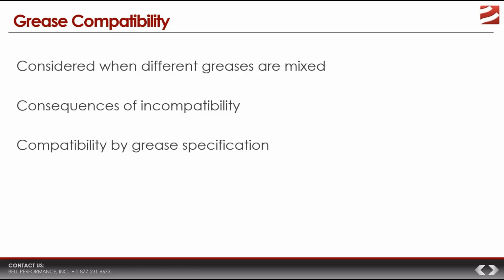Mixing incompatible greases can have dire consequences. If two greases are incompatible, when they come in contact with each other in a lubricating environment, they will react together and cause the base oil to separate from the thickeners. When this happens, the base oil doesn't have anything holding it in place anymore, so you get oil oozing or running out of the area where it was applied. You can probably guess the bad things that follow from that.